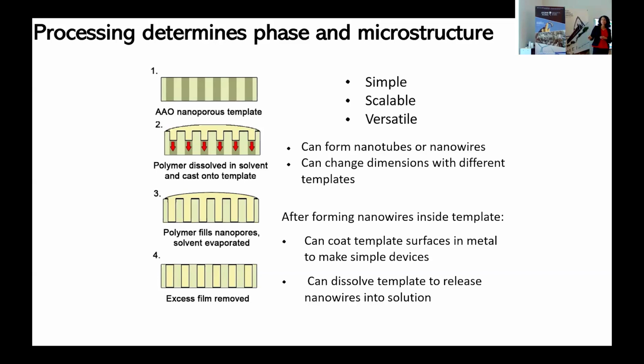Once the polymer fills the pores, then we either do a controlled evaporation if it's from solution, or a controlled solidification if it's from the melt, until you're left with just the template with loads of these nanowires grown within it. You can see that they're all nicely aligned because they're grown within this nano-confined geometry. So it's quite a simple, scalable, versatile technique.